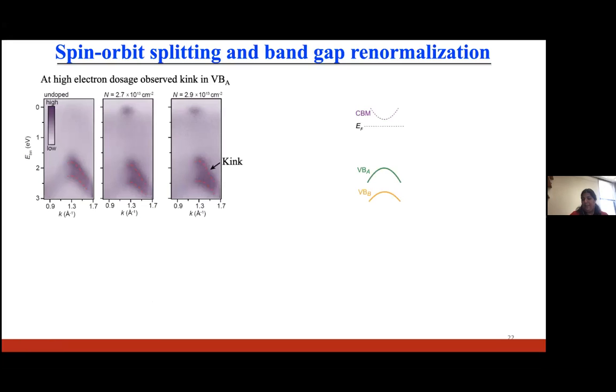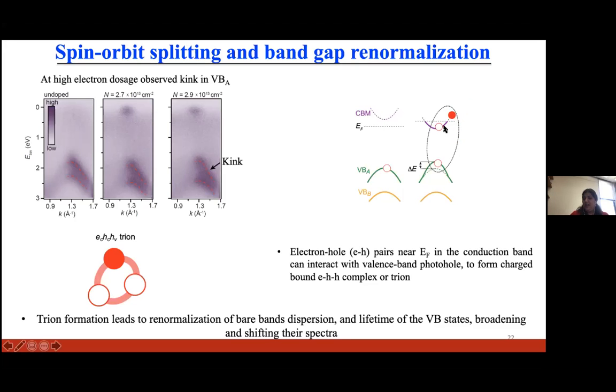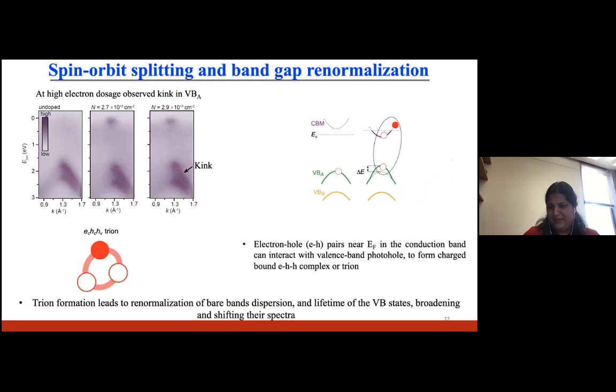So in the ARPES, when we shine light, we get this photo hole in the valence band. Now when we put a lot of electrons in our system, we can end up in a situation where near the Fermi energy, we have an electron hole pair, and this electron hole pair in the conduction band can interact strongly with this photo hole in the valence band. Then because of the strong Coulomb interactions in these single layered WS2, they can form this charged electron hole complex, which we call a trion. And so we believe that trion formation here leads to renormalization of the bare bands and causes this enhancement of the spin orbit splitting.